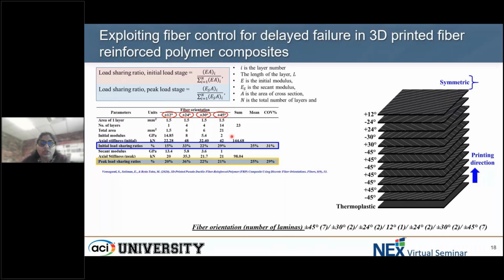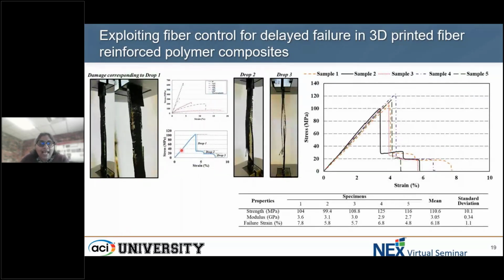So if you see the total number of layers here, we have about 14 plus 4 plus 4 plus 1, so about 23 layers in total that have been 3D printed. So if we look at this particular preliminary design, we did achieve somewhat of a progressive pseudo-ductile. If you remember, I showed you how ductile, progressive, pseudo-ductile, linear work. So we see a nice linear behavior in the beginning until the tensile strength of the composite has been achieved.